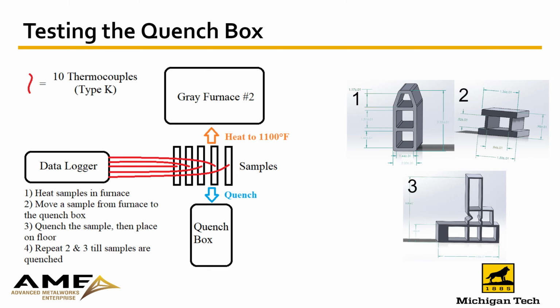To make sure our quench box is going to work as designed, we're going to test it using one of 3 different samples provided to us by ShapeCorp. We're going to heat them up in Gray furnace number 2, and then quench them in the quench box. For each part, we have them thermocoupled so that you can read the temperature across the length of the part.